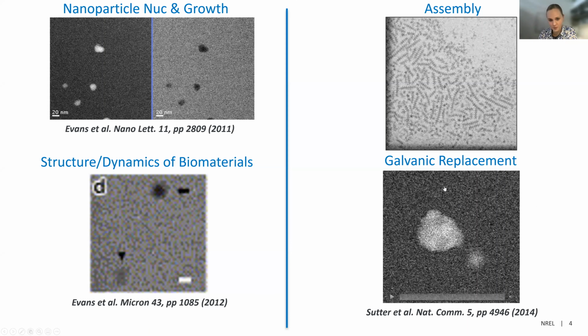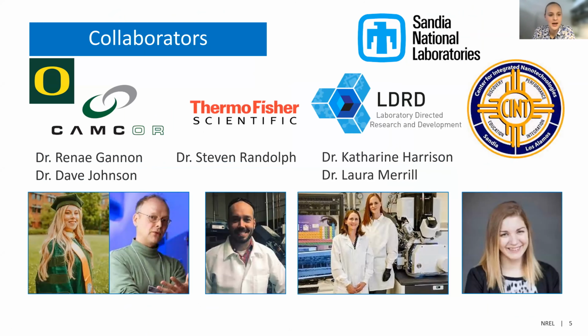And then another work was looking at galvanic replacement, where we were putting palladium on top of silver nanoparticles, where the palladium would reduce by stealing the electrons away from the silver. And so you get this silver core that would be eaten away, and then a mixture of silver and palladium on the shell. So these are all things that you can do inside the microscope if you're unfamiliar with liquid cell transmission electron microscopy. But for our work today, I want to highlight my collaborators. So this work wouldn't have been done without meeting Dr.